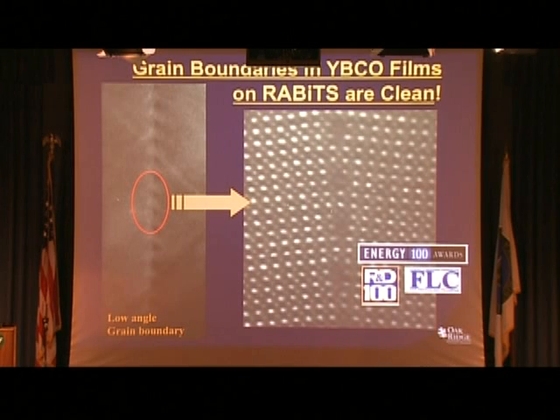The reason why these materials work well is because if you were to look at a grain boundary within the superconductor, you get a classic description of what is defined as a low-angle boundary with a pile of dislocations.